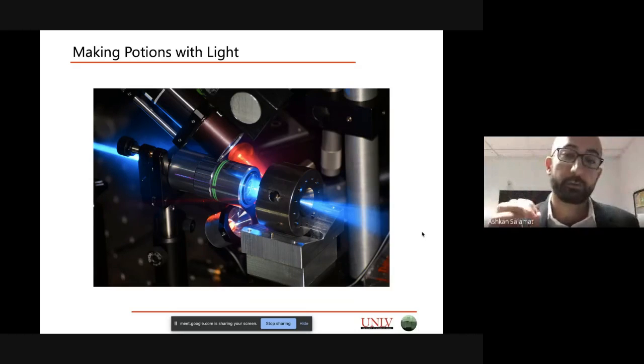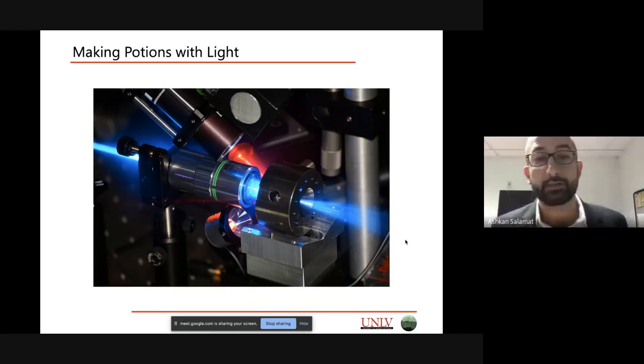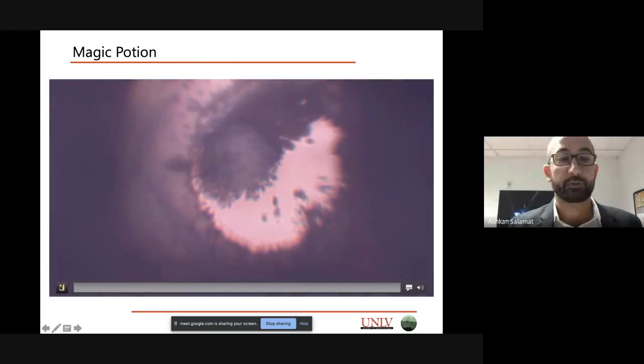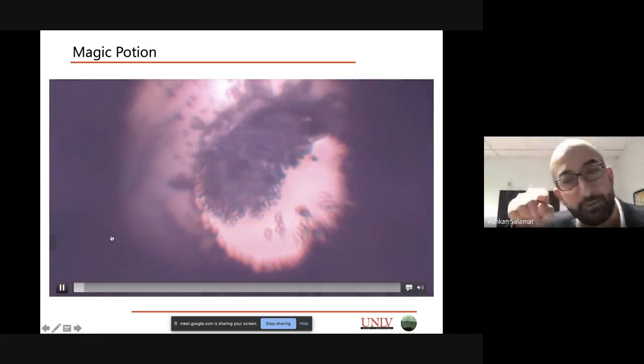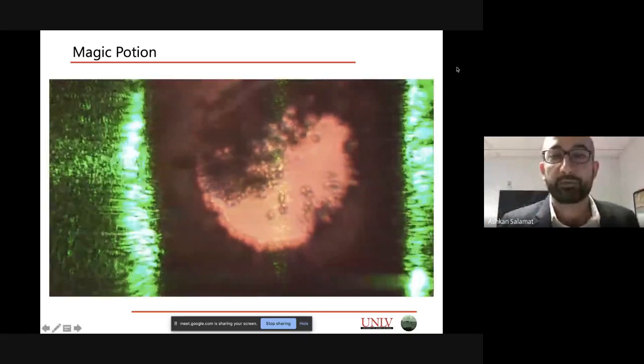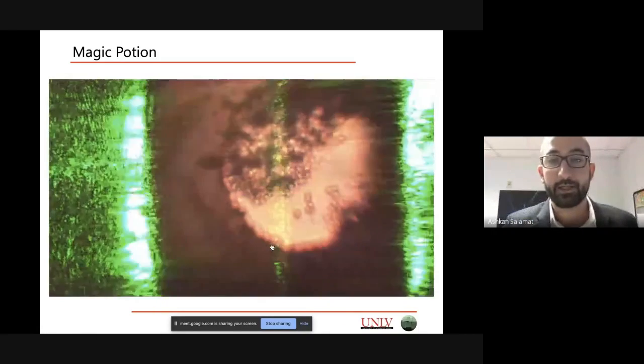So we put carbon, sulfur, and hydrogen into a diamond anvil cell. This is two diamonds opposing each other while our sample is stuck in the middle. Because the diamond is optically transparent, just like this photo is showing, we can shine light into our chamber. And for this material, we use light to transform the carbon, sulfur, and hydrogen into our magic material. This is just a short demonstration. This is us looking through the top diamond into our sample chamber. This ring on the outside is that metallic ring that stops the sample from slipping outwards. What you see with this powder here, this black soot, is carbon and sulfur, an elemental mixture. And this clear material here is hydrogen.